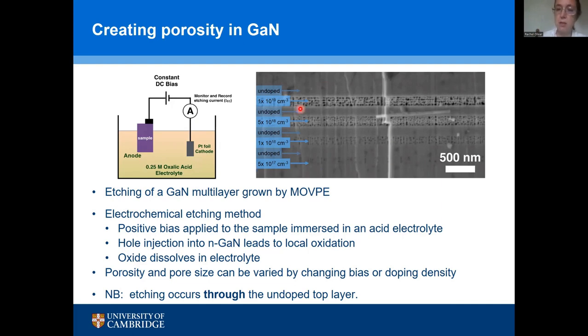So this is one of the very early samples we porosified. This is a process which can only happen when we have this electrochemical circuit completed. So undoped layers, like at the top here, basically don't etch because they show no conductivity. We can't flow current through them. And then more highly doped layers etch more, and rather low doped layers etch less. And that gives us one handle on controlling the porosity in our material.